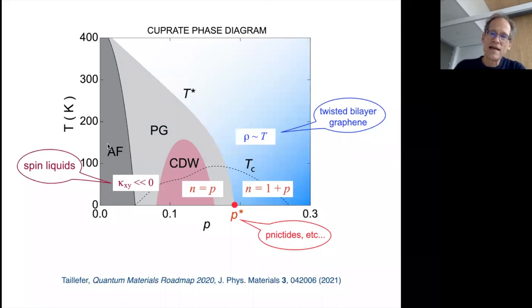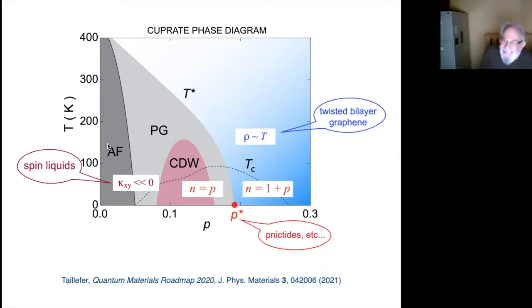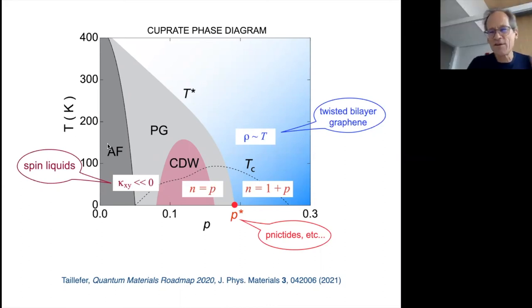the thermal Hall effect is by sending heat current along the c-axis. You see, these are 2D systems, electronically and magnetically. So the magnons have high velocity in the plane, but almost zero velocity perpendicular to the plane. So we did a thermal Hall effect along c, and we found an isotropic result. So basically, the only thing that's isotropic are the phonons. So that's the part I skipped quickly in my talk. But thank you.